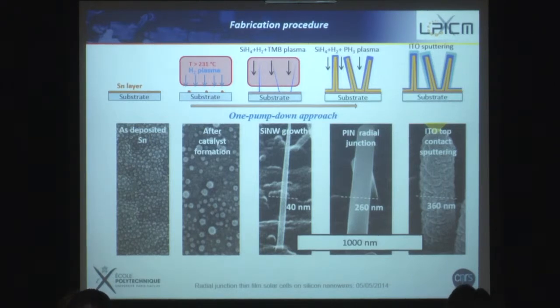In fact, it is different. If you look, then you get disorder in the structure. These are the steps which are now used by Sumyadip Misra at Ecole Polytechnique, who is growing the structure using thin catalytic particles, and then he grows the nanowires with a diameter of about 40 nanometers. The length might be a few microns, and when they are coated by about a 100 nanometer thick absorber layer and then with a top TCO coating, they will finally look something like this.